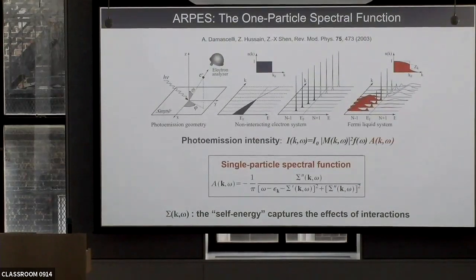Photoemission, this is a historical slide, goes back to the time I was a postdoc with ZX at Stanford, and basically is a technique that allows you to follow a band dispersion in a solid by removing electrons. And in fact, by doing that, you're really probing directly the single particle spectral function. And so what you do in an experiment in the old days, we would change the relative angles between sample and analyzer and follow the dispersion of these peaks, which you can follow up to the chemical potential, where we have no more electrons, and so you can't see and follow the unoccupied part of the band dispersion. And if you go and look beyond just the location of the peaks, you also look at the detail of the line shape, you start getting information about the self-energy. And you guys here are really experts at that.